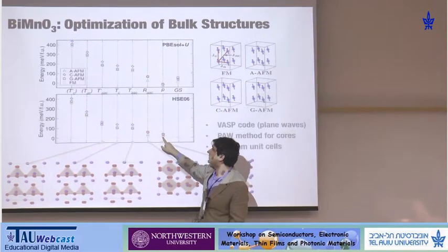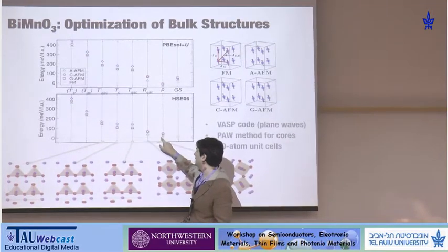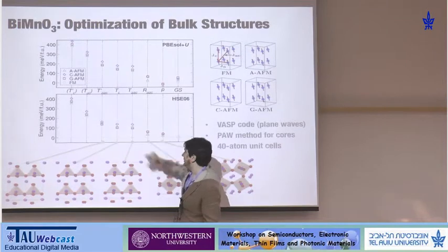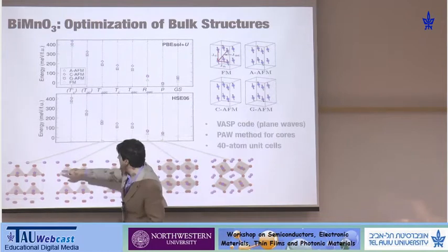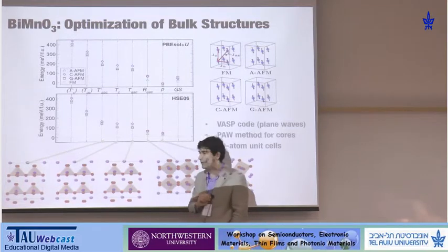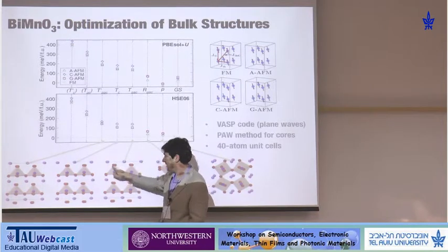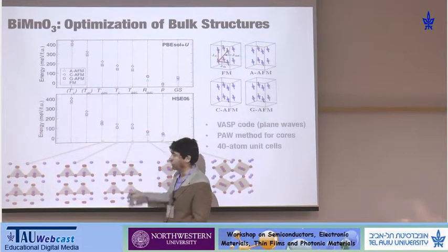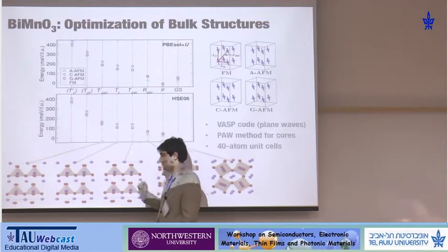non-polar, so not ferromagnetic and also not paraelectric phase, and then we get something that looks like the ground state of bismuth ferrite, and then we get these phases that are particular perovskite phases in the sense that it's not really a perovskite anymore if you impose that a perovskite must have an octahedra. The octahedra move up so much that they break this bond, so what you have is pyramids. This has been seen before in one material, which is bismuth ferrite.